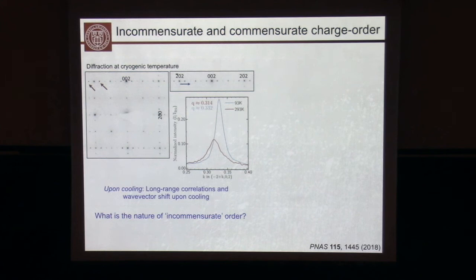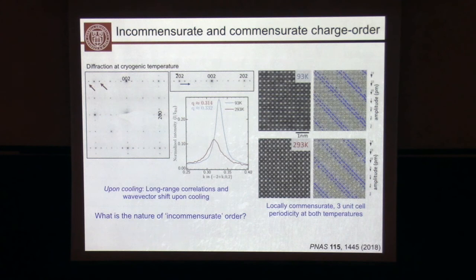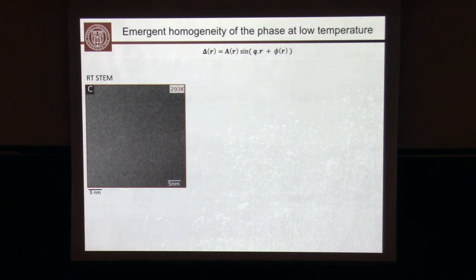First we can do our local probe, and it turns out, contrary to this picture which shows a change in K spacing, the local order is identical. As far as we can tell within the error, there's a 3-unit cell periodicity at both temperatures. So how can you reconcile this local picture with the global picture of the diffraction? The answer is that at larger length scales, we have phase disorder. Here is the picture over maybe 30 nanometers, where we can apply the same methods to extract the displacement field, and we have quantitatively extracted the phase.